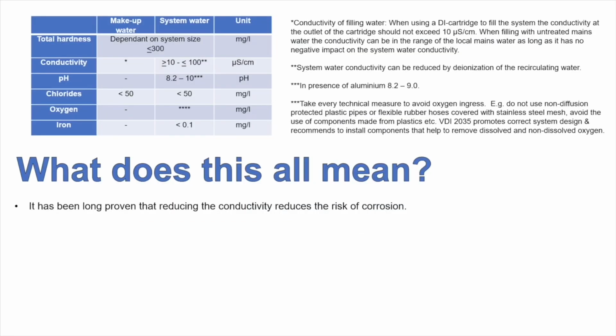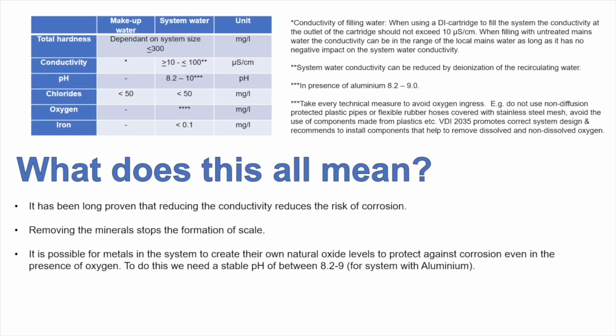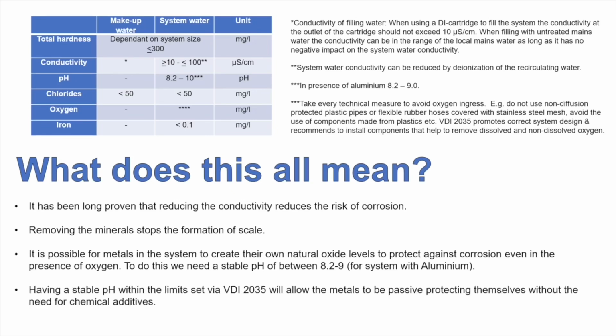What does this all mean? It's long been proven that reducing the conductivity reduces the risk of corrosion. Removing the minerals stops the formation of scale. It is possible for metals in the system to create their own natural oxide levels to protect against corrosion, even in the presence of oxygen. To do this, we need a stable pH of between 8.2 and 9 for systems with aluminium. Having a stable pH within the limits set via VDI 2035 will allow the metals to be passive, protecting themselves without the need for chemical additives.